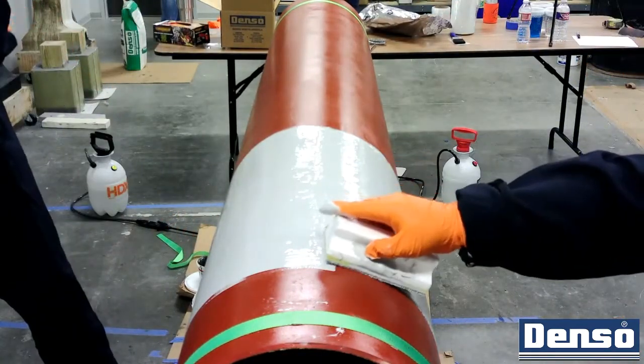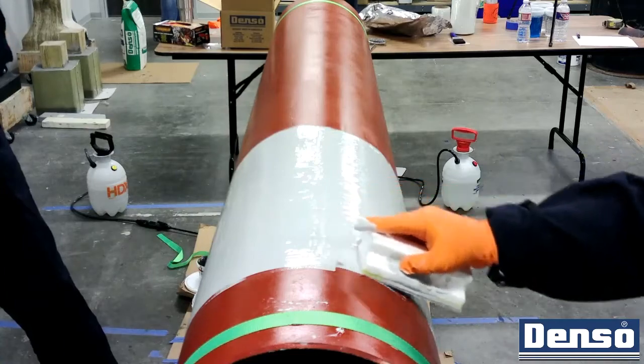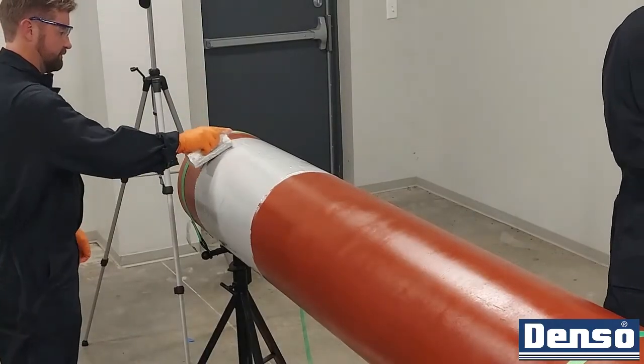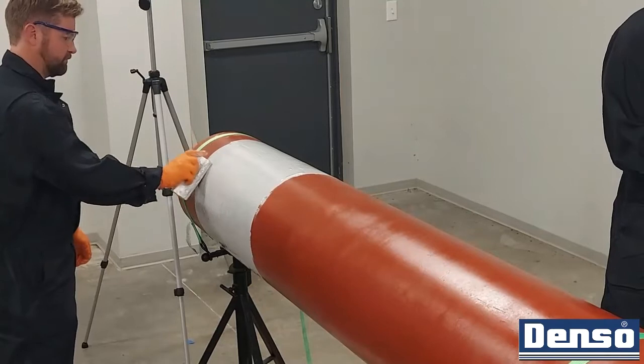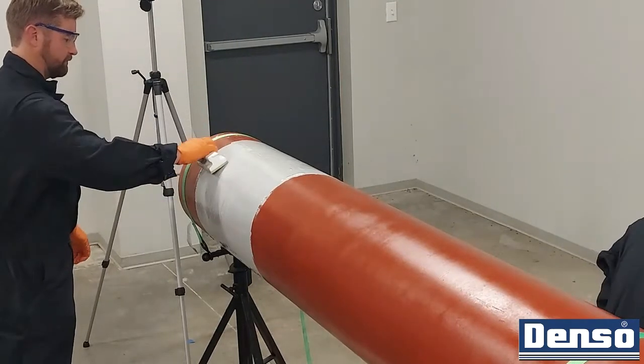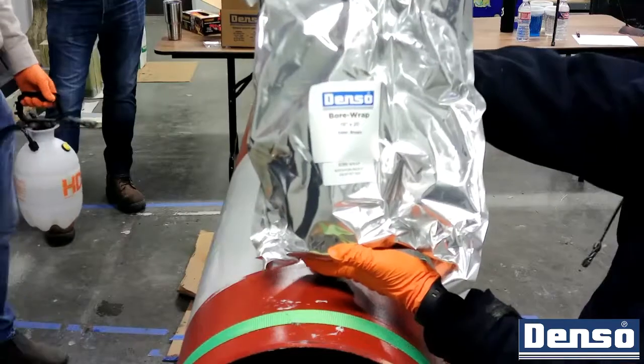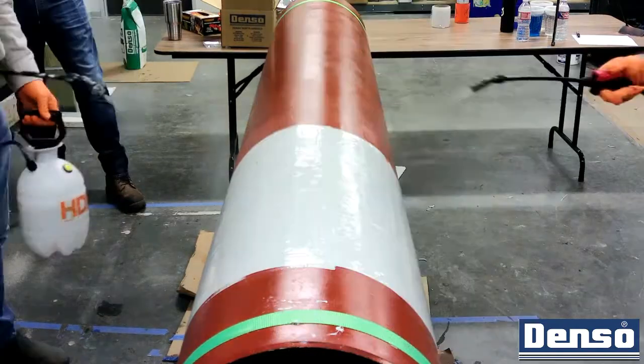Once the epoxy has become slightly tacky, begin the bore wrap application by wetting the surface of the area that the roll will be applied onto using a water sprayer. Water needs to be continuously sprayed onto the surface and underbelly of the roll as it is being applied.